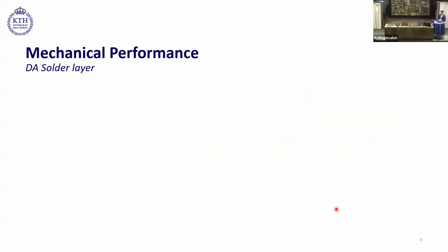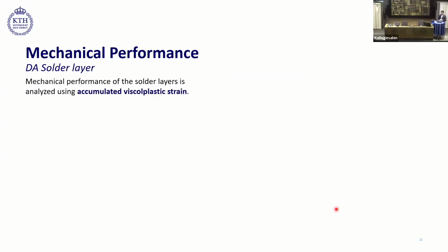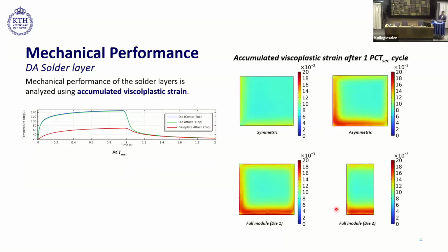Now coming to the mechanical performance. First, we will go through the die-attached solder layer. For the solder layers, we used accumulated viscoplastic strain as a performance criteria. Here, we are looking at the viscoplastic strain accumulation in the die-attached solder layer calculated during one cycle PCT-SEC. In symmetric condition, the viscoplastic strain accumulation was a bit lower. However, in asymmetric condition, the strain accumulation increases. And if you look at this edge region, we see that this area experiences very high viscoplastic strain accumulation. The same observations were made in full module.